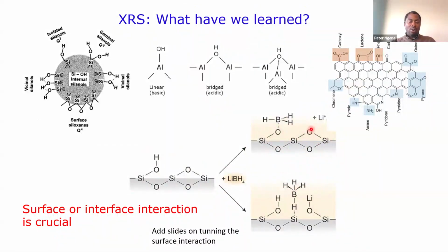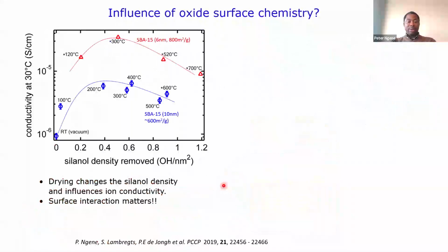But what we do know and we do think is that it's highly defective. And because it's highly defective, the defect concentration is very, very high, so we have high ionic conductivity in these materials. So the surface interaction matters.